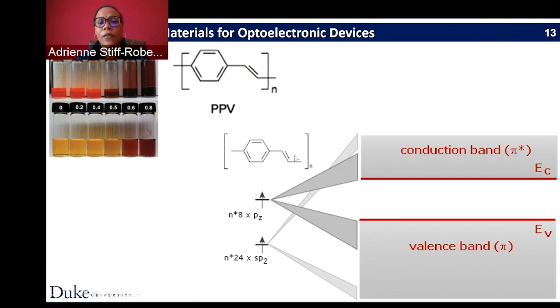But because you have this repeat single, double carbon bond, you can introduce a band structure into a particular class of polymer materials, and these are known as conjugated polymers. And so these conjugated polymers then can be a matrix for the inorganic nanoparticles to try to make optoelectronic devices based on these quantum dots. So it was this interest in quantum dots and trying to have a better behaved quantum dot material system. One thing I didn't mention, because the colloidal quantum dots are spherical, if you want to predict what the properties will be, it's a lot more straightforward to do that with a spherical quantum dot. So I was interested in this.